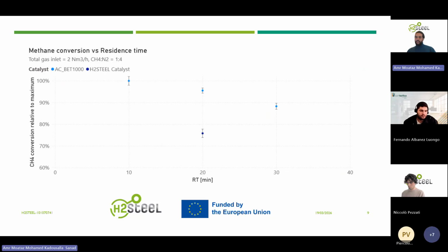And this is the last slide of my presentation for today, where I would like to show you the results from the 4 different experiments and their relation to one another. All these experiments were conducted at the maximum gas inlet operating conditions of 2 normal cubic meters per hour and 20% methane inlet percentage, with the other 80% being nitrogen. In light blue, you can see the commercial carbon used as a catalyst, as a benchmark for the other catalysts that are then produced and used within the H2STEEL project.